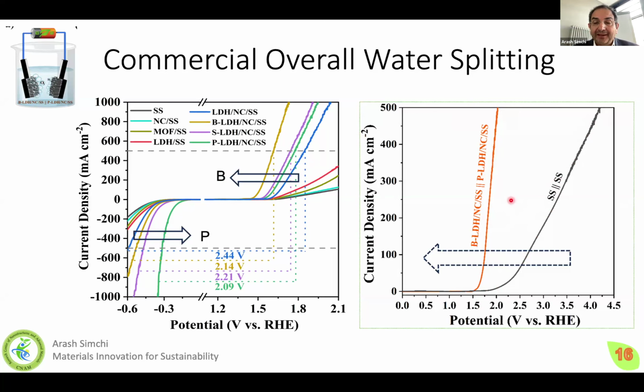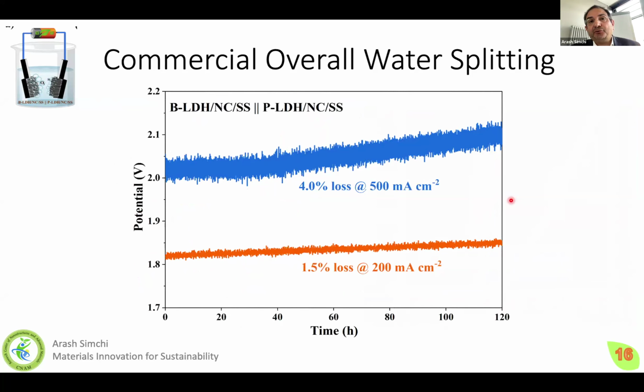It's really quite significant. The important point is always, is it stable? Because we would like the electrolyzer to work for 10,000 hours at least. And I would like to show you that our system is relatively stable, as you see here, for a long time, even at a 500 milliamp per square centimeter current. You know that many papers when published only show data in the range of 10 milliamp per square centimeter. I would like to show you 500 milliamp, which is good enough for a small scale electrolyzer, showing that this approach, learning from nature and using sustainable materials, really yields high current density, low overpotential, and a high hydrogen rate. This is a good example of what we are doing in our work.